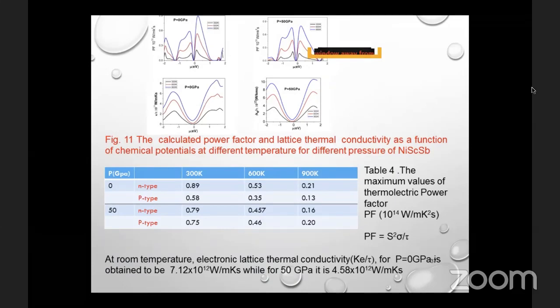Thermal conductivity is caused by electrons and lattice vibration. A small value of lattice thermal conductivity means better performance for a thermoelectric device. The thermal conductivity contains the contribution of the electronic carriers and phonon vibration. Only the electronic part of the thermal conductivity can be determined by means of the BoltzTraP code. Electronic thermal conductivity as a function of chemical potential at different pressures is also given in Figure 11.